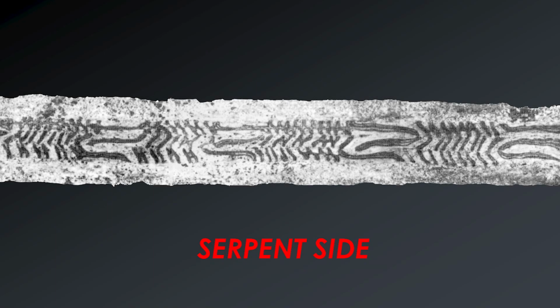Next, on top of the checkers pattern, there is a section damaged by corrosion. Sadly, this area contained an inlay of which I could only clearly see that it ends in 1 or 2 vertical straight inlay lines. After the inlay, a 3-bar section of alternating chevron and its straight laminate can be seen. This pattern repeats 4 times. The grinding is very shallow. No more than 10% of the rod can be removed before this pattern turns into something else, which, by the way, does happen in this blade.